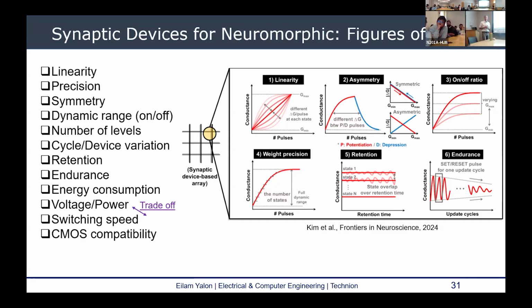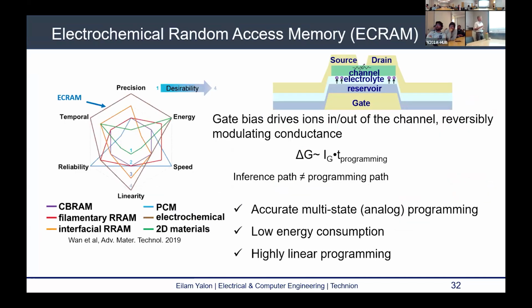Unlike conventional memory elements, we have distinct levels. Two levels are sufficient, like the two states which we have in our ferroelectric devices. For synaptic devices, we would like to have kind of analog behavior with a large number of states and good tunability and precision of those conducting states, with good linearity in terms of the change in conductance versus the number of pulses, and good symmetry between increasing and decreasing the conductance, or potentiation and depression, and so on and so forth. So for these types of devices, we're looking for something that shows a very gradual and linear change in the conductance.